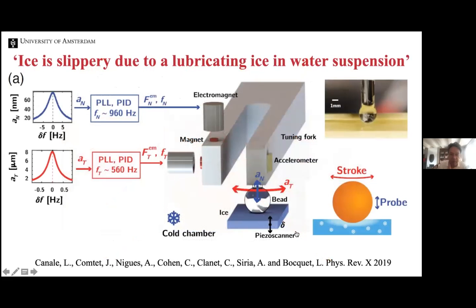Fortunately, there was a very clever experiment by my French colleagues, headed by Lydéric Bocquet, published 1.5 years ago in PhysRevX. And they had a very nice experiment where they have what they call a tuning fork with a bead attached to it, and the bead slides over ice. And what you measure is the change in eigenfrequency of the tuning fork when the bead touches the ice. And it turns out that the change in frequency has a real and an imaginary part, suggesting that the ice is actually viscoelastic, which complicates things even more.